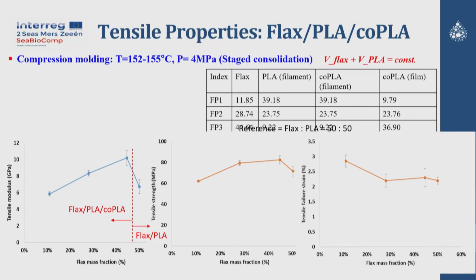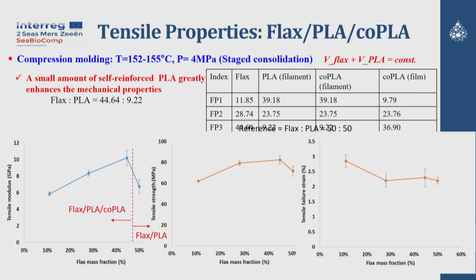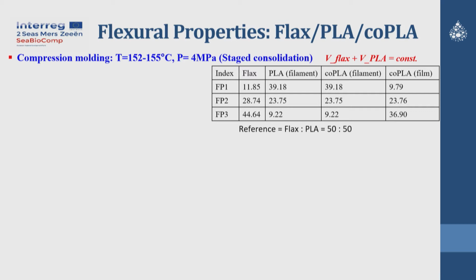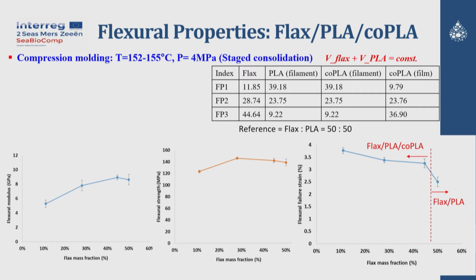You can see that compared with the conventional flax PLA composite, we could increase modulus and strength, and we could obtain almost the same tensile failure strain. So the result is that with just a small amount of self-reinforced PLA, we can greatly enhance the mechanical properties. And then we can conclude this kind of tertiary composite is better than the binary composite of flax PLA. And if we measure the flexural properties, we could obtain almost the same conclusion.